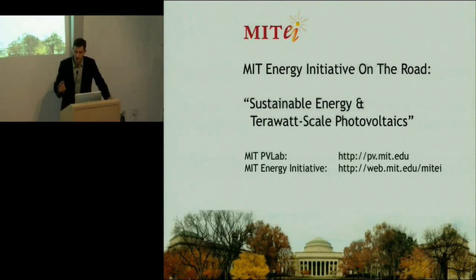Sure. So the question was, the dollar a watt on the module level, the premise here was that First Solar produces solar cell modules that are $1 a watt on the module level, but because of the high installation costs, these are low efficiency panels, because of the high installation costs required, you wind up with an installed system cost much higher than $1 per watt, and it's still not cost effective. So as one of the requirements that I had earlier in the slides, a baseline efficiency of 15% was what we're targeting. And with those sorts of efficiencies, if you have $1 per watt, the installed costs become lower as a total percent. So there is an element there embedded. Perhaps I didn't express it clearly enough.